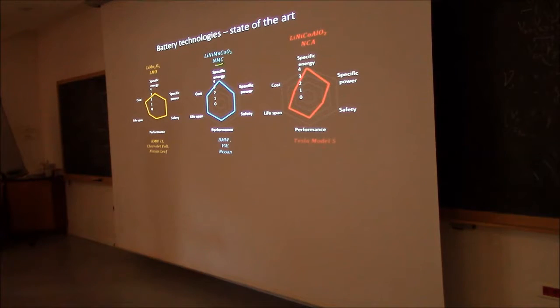Here in the middle you can see NMC, nickel, manganese, cobalt, and that's a type of battery which is being used by BMW, Volkswagen, and Nissan for their cars. So what's Tesla using? Tesla was using for a long time the NCA, nickel, cobalt with aluminum. They just chose aluminum instead of the manganese, but it's a relatively similar material with some small differences that they chose specifically for this. And then you have other materials where there is no cobalt in, this lithium manganese oxide, which is being used by, for instance, BMW and other cars, Chevrolet or Nissan.